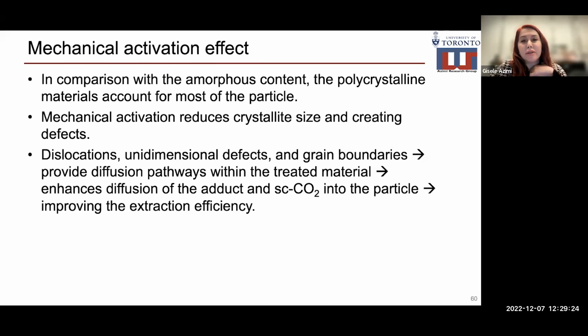Mechanical activation reduces crystallite size and creates defects. Dislocations, unidimensional defects, and grain boundaries provide diffusion pathways within the treated material. This enhances the diffusion of adduct and supercritical CO2 to the particle, which improves the extraction efficiency.